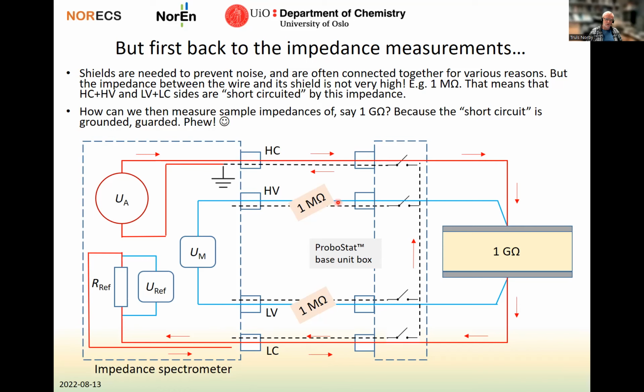So in a way, we are now short-circuiting the two blue wires, even if they are supposed to pick up the voltage over a sample with 1 gigaohm. The two blue wires are short-circuited through their own shields, which are connected together. How can we then measure the sample impedances of such magnitude as 1 gigaohm? And the answer, very shortly put, is that this short circuit that goes via the shields are connected to ground and therefore eliminated from the measurement. That is not a very complete explanation, but it is a short explanation. So the impedance spectrometer is able to measure correctly even if it has a short circuit via its shields. And therefore you may often forget that your measurement setup has these short circuits.